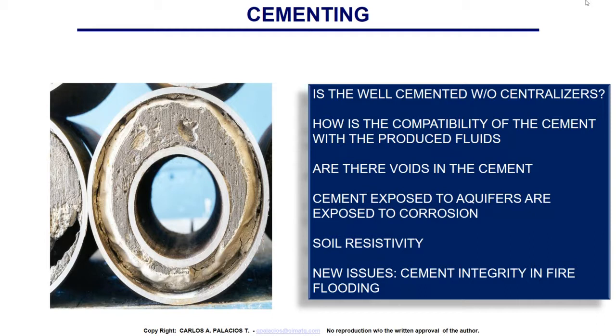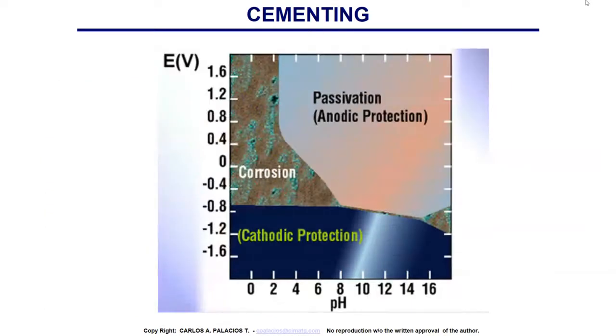Okay. Then when I have the cement all the way to the perforations, I perforate, I'm cracking the cement, and I can have corrosion around the perforations. Okay. Also soil resistivity. I think I have a slide coming up to talk about that. But this is what I was talking about with the pH. See, we are in the passive region. This is the natural potential of a steel. And between a pH of around 10 to 14, which is the pH of Portland cement, we are in this region of passivation. If we destroy that passivity, corrosion starts on the outside of the casing.